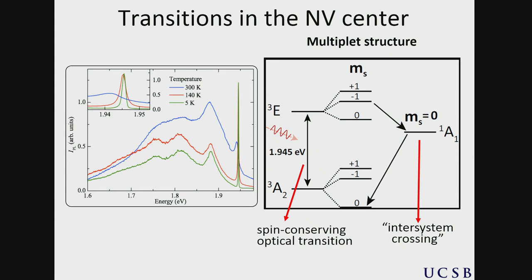Now, if you look at this in more detail and look at the magnetic structure, you actually find that there are a number of possible transitions between these magnetic sublevels possible. And it turns out that there is actually another possibility instead of this optical transition to go from the excited state to the ground state via this intermediate level. This is referred to as the intersystem crossing. And these transitions actually are non-radiative transitions. And they are very important because they actually enable you to initialize the system in this MS equal zero ground state so you have a particular spin state for the center.